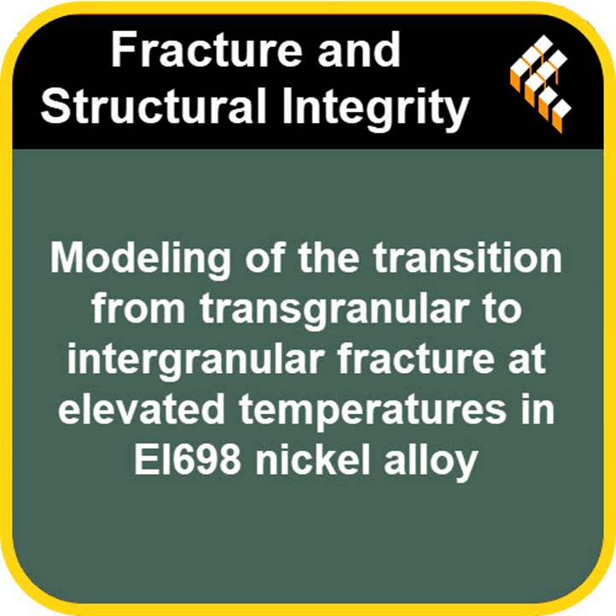It shows that there's an additional energy required to change the crack trajectory from its initial path. So if a crack starts inside a grain, it takes a certain amount of extra energy to make it suddenly turn and follow a boundary, even if that boundary is weaker. It's a sophisticated point about fracture mechanics. Inertia matters, in a sense. That's fascinating. It's not just following the absolute weakest path instantaneously.